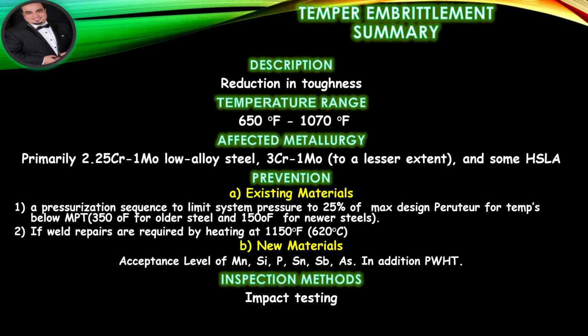The summary of temper embrittlement. Description: reduction in toughness. Temperature range: 650 degrees Fahrenheit to 1070 degrees Fahrenheit. Affected metallurgy: primarily 2 1/4 chromium, 1 molybdenum, low alloy steel, 3 chromium, 1 molybdenum, to a lesser extent, and some high strength low alloy steel.